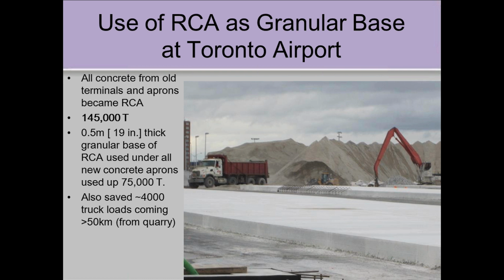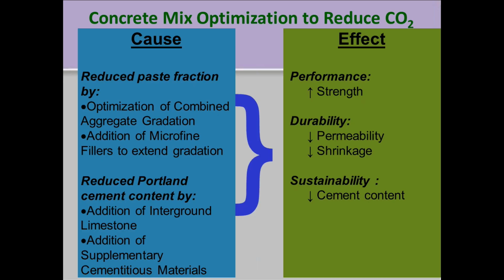And apparently they found that recycled aggregate makes a great granular base, and it's actually cemented up and improved the structure of that pavement. It also saved a lot of trucks coming down the highway from over 50 kilometers away from the closest quarry to bring aggregate in for that purpose. So it had a number of uses, and they're slowly using the rest of it. You can actually see the residual piles if you look certain ways at the airport, on the edge of the airport property. So we can do a whole bunch of good things to reduce CO2.